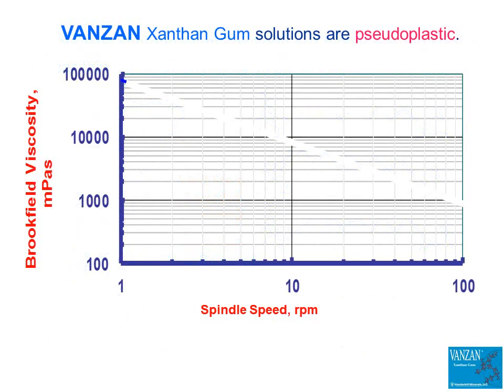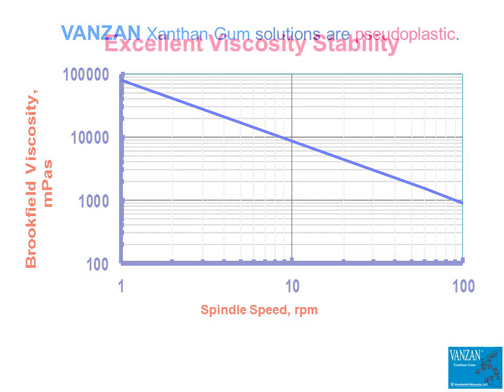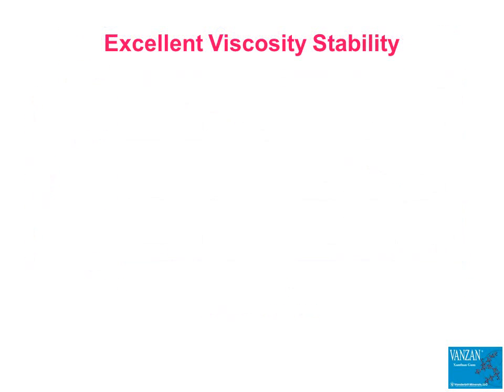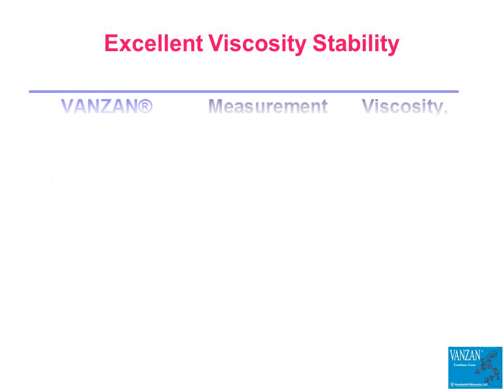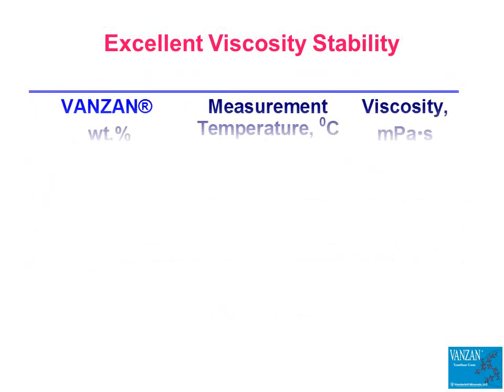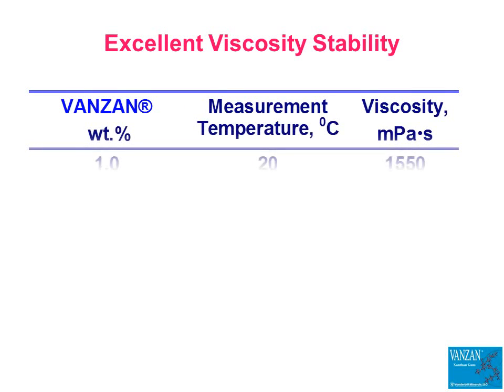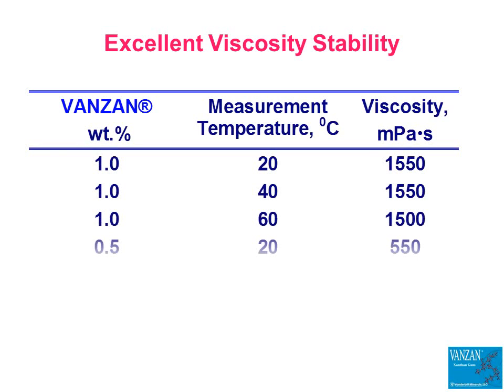The viscosity is very high when the composition is at rest or subjected to low shear. At high shear, which is frequently encountered when the formulated product is used, the viscosity is significantly lower. The rheology of aqueous xanthan gum solutions is remarkably stable over a broad temperature range, as shown here. The viscosity and yield value of compositions containing xanthan gum do not change significantly between ambient temperature and 60°C.